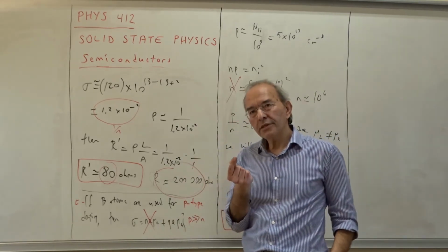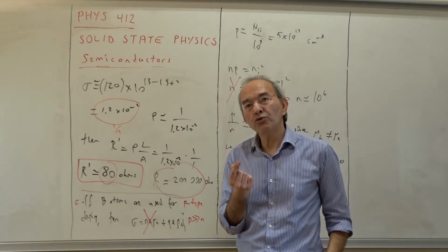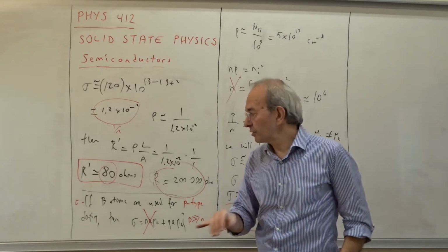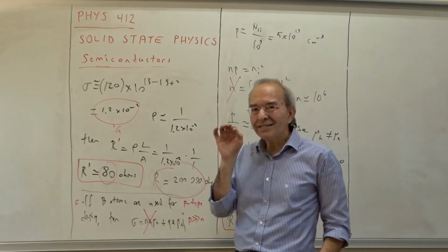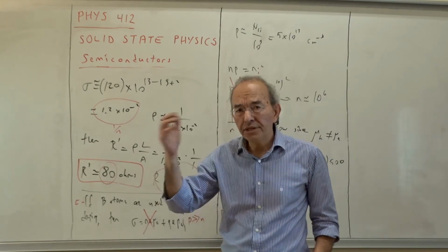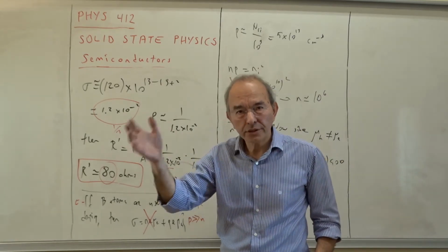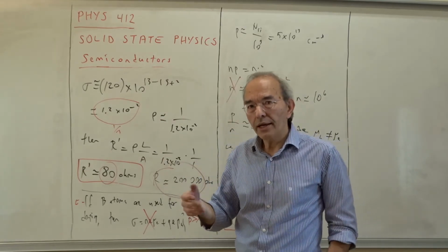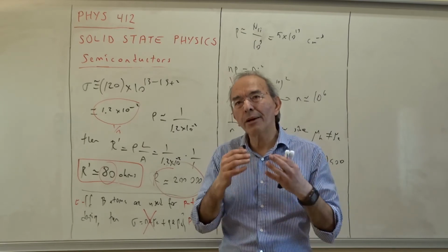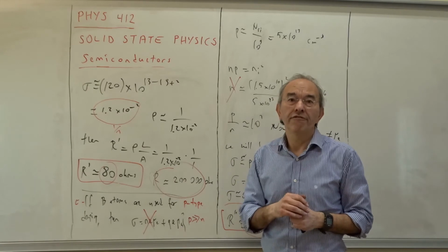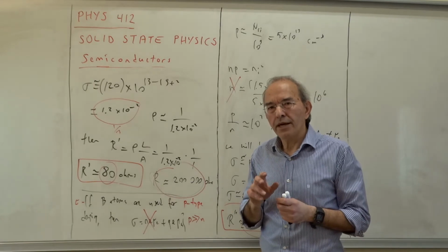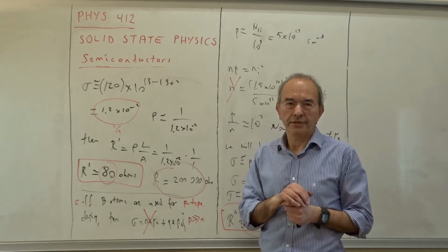So this single object having a volume of 1 cubic centimeter of silicon, in the intrinsic case has a very large resistance of 200 kilo ohms, but by just introducing some very, very small amounts of extrinsic elements, such as group 5 or group 3, as a result of this very little introduction, the resistance drops abruptly to a much, much smaller value. So you can play with the resistivities and conductivities by just adjusting the level of doping.